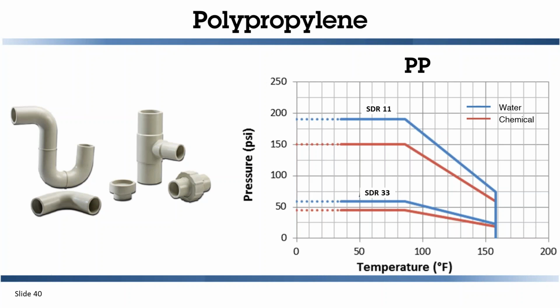So let's look at the top two lines here for SDR11 system. SDR11 for water is approaching 200 psi. For chemical applications, we really take that down to 150 psi, which covers a lot of the tenacious chemicals that we're transporting in the systems. That gives you a 50-year life for the chemicals that we say are compatible. With SDR33, we have a 55-60 psi and about a 45 psi rating for the chemical applications.